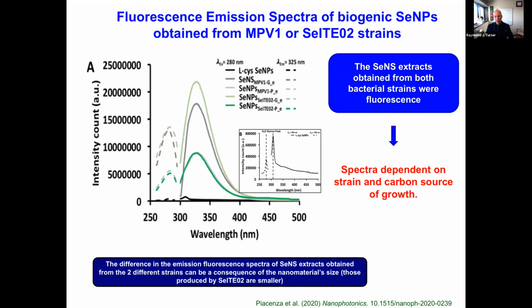One thing that we were very surprised of in the literature, selenium nanoparticles are not considered to be very fluorescent. Here is a chemically synthesized selenium nanoparticle. Very, very little. This is just a bit of a Raman scattering peak, but hardly any fluorescence. You've got to really zoom in to see it.